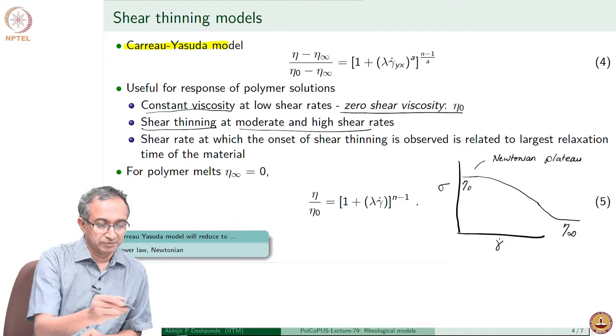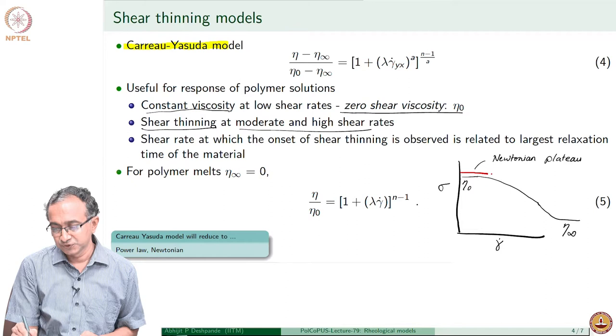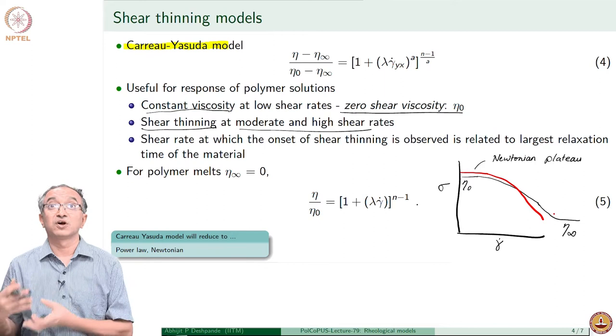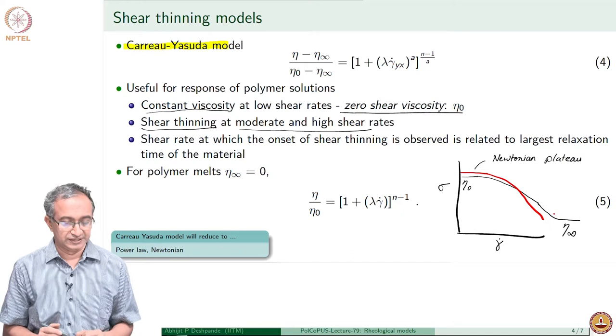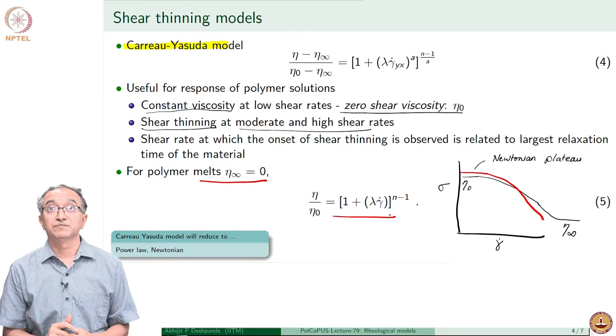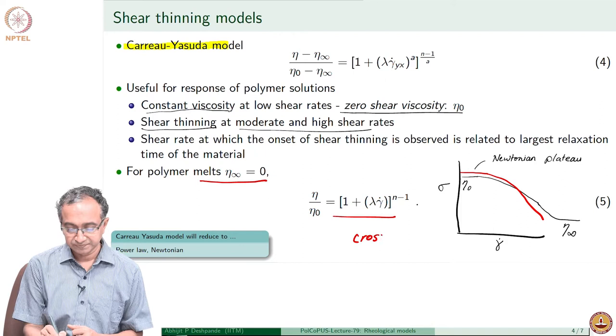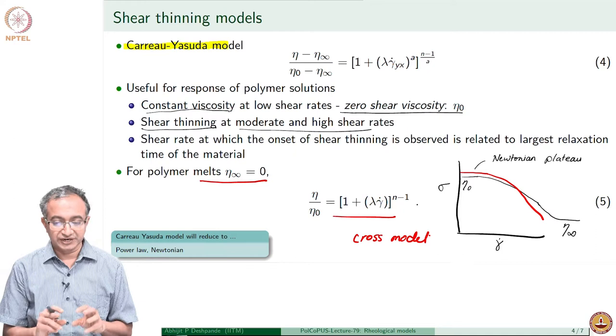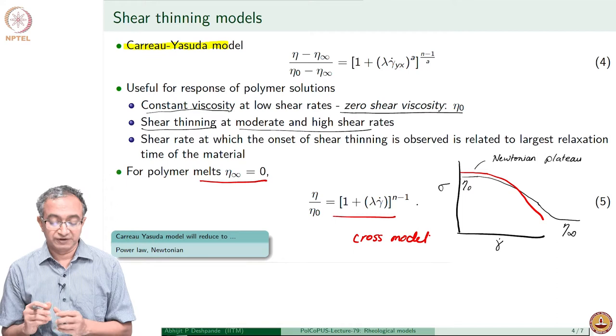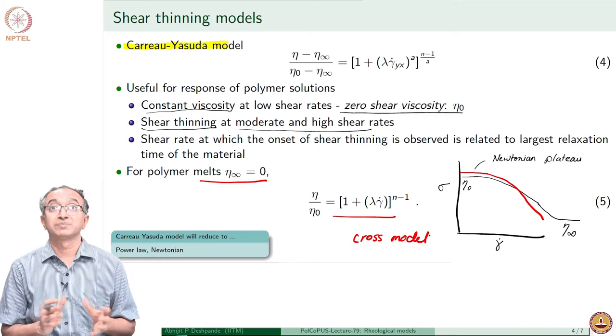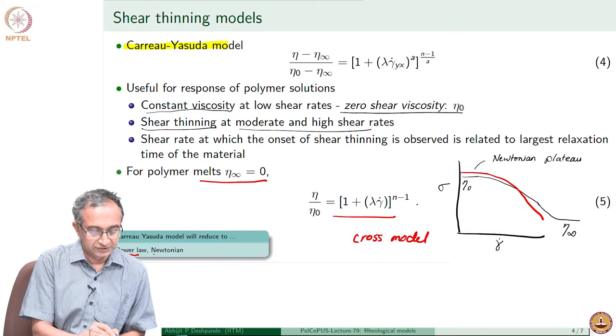In the case of polymer melts, there is only polymer and no solvent present, so only shear thinning is observed but there is a Newtonian plateau at lower shear rates. For polymer melts, we can generally modify this model by setting eta-infinity to zero, and then we get the simpler version of the Carreau-Yasuda model, which also goes by the name of the cross model. As an exercise, try to see what happens if you set lambda to a large or small value, or n equal to 1 — you should be able to show that the Carreau-Yasuda model reduces to a power law or Newtonian fluid model.